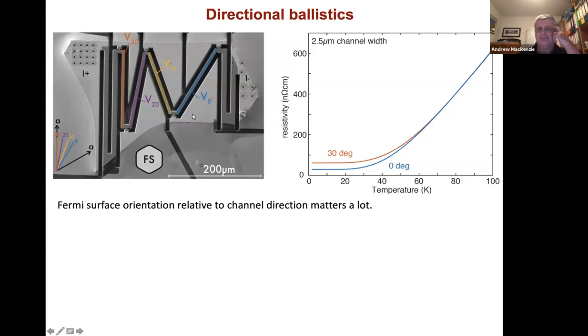So if you look at the graph on the right, what you see at 100 Kelvin is, showing you here the two extremes, in the same crystal, of running the current down a channel at 30 degrees, where the flow direction is oriented that way relative to the Fermi surface, or running it in this notation at 0 degrees, where the flow direction is perpendicular to one of the Fermi surface faces. Now, in a triangular lattice metal, basic symmetry considerations tell you that transport has to be in-plane isotropic. So when we're up at 100 Kelvin, it's no surprise: there we've got strong phonon scattering, strong enough to make the mean free path much shorter than the device size. So we're in the ohmic regime and we see the same resistivity independent of direction.